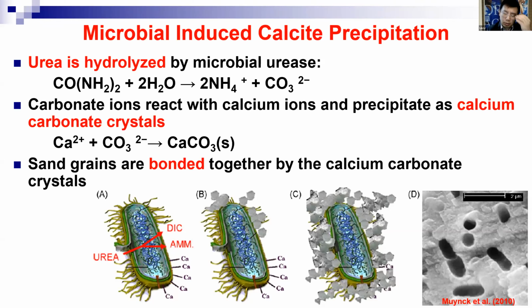The reason is that this bacteria has one very unique thing: it can hydrolyze urea, and when it hydrolyzes the urea, it releases carbonate ions into the solution. If the solution has calcium ions, which can come from adding calcium ions to the solution, or from, for example, the fly ash, which may have a higher calcium component, that helps the solution precipitate calcium carbonate.